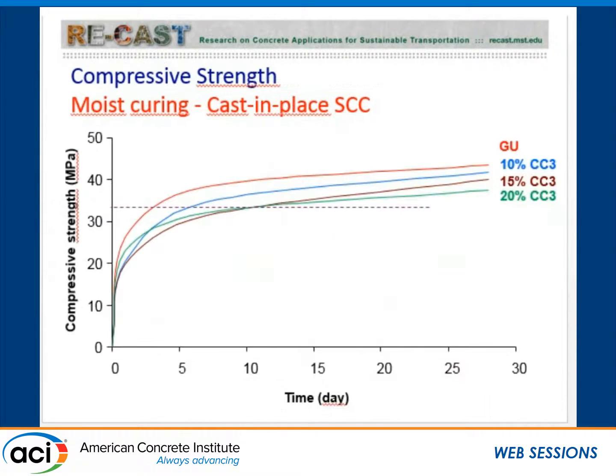I'm showing here the compressive strengths, moist curing until 28 days, and this is for the cast-in-place SCC, water to powder ratio 0.42, using type 1 cement or GU cement, and then 10, 15, 20%. And as expected, later age strengths are hindered a little bit by the use of the limestone filler.